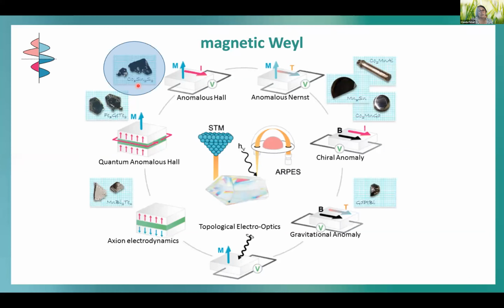I want to show here only one example. Typical signatures of these magnetic Weyl semimetals are also the chiral anomaly - nobody measured the gravitational anomaly, we should do it, we didn't do it yet - and the anomalous Hall and anomalous Nernst large responses in the magnetic field, and for sure STM and ARPES investigation to prove the Fermi arcs in this material.